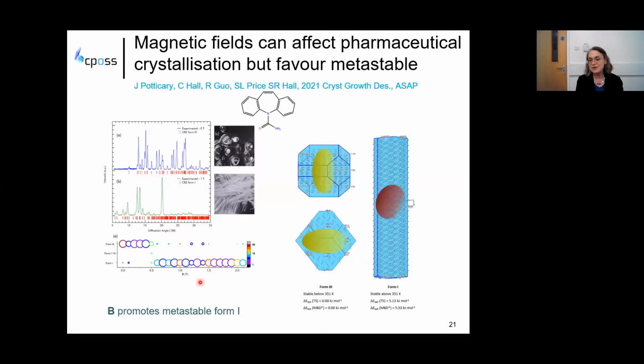In Bristol, they built apparatus where the crystallization experiment was identical unless you switched the field on. And this represents one set of results where the color shows you how many experiments were done, up to 60 with no field. And the size of the bubble tells you how much of that polymorph was obtained and what proportion of the experiments. And this was one of the most clean-cut examples where once you got above 0.5 Tesla field, then suddenly you've got a preference for crystallizing out the metastable form. We have unpublished some ideas of why that may happen, but it's certainly not a thermodynamic effect and wasn't the way around we'd really have liked it to have been.